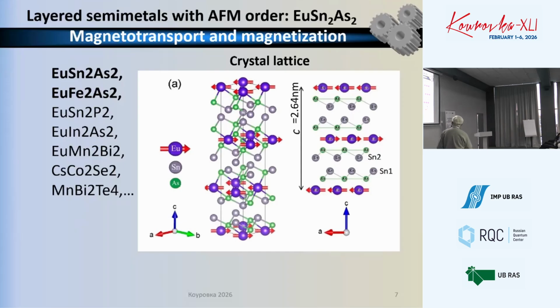has a layered structure where layers of europium alternate with layers of tin and arsenic. The tin and arsenic supply electrons to the conduction band, and europium atoms are responsible for the magnetic properties. Pay attention that it's a huge distance between the europium layers, so that the magnetic lattice, the magnetic unit cell, is huge. It's doubled the crystal.